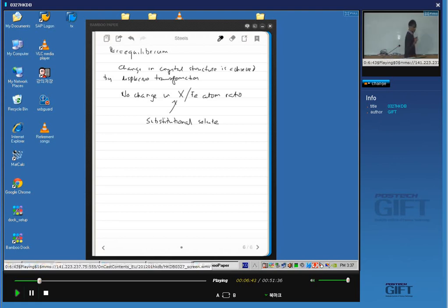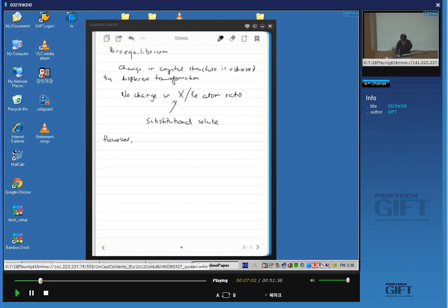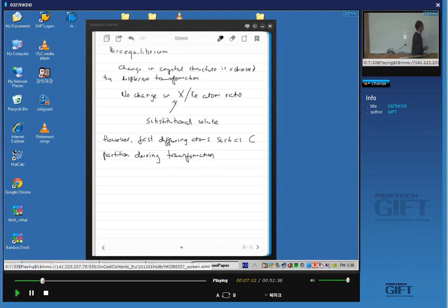However, subject to that constraint, the carbon atoms will diffuse during transformation and end up in the phase where they prefer to be. In the case of steels, the carbon will partition into austenite. Fast diffusing atoms such as carbon will partition during transformation. So this transformation will have all the characteristics of a displacive transformation — a large shape deformation with a shear, a lot of strain energy, and because of that a plate shape.